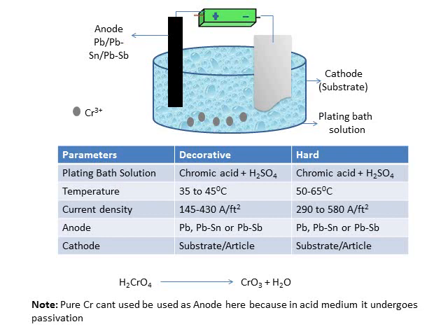The temperature in the case of decorative and hard chromium plating is about 35 to 45 degrees centigrade and 50 to 65 degrees centigrade respectively. Current density, that is current applied per unit area, is 145 to 430 amperes per square feet and 290 to 580 amperes per square feet. The difference in temperature and current density between decorative and hard chromium plating is due to the fact that in both cases, a different thickness of chromium is to be deposited. In both cases, the substrate or article will be the cathode.